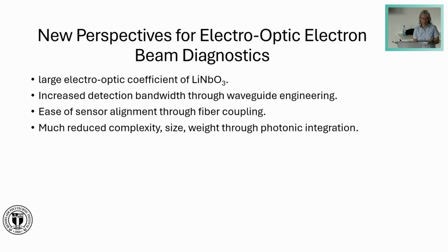If I come back to the new perspectives provided by thin film lithium niobate, it has a large electro-optical coefficient. It is about 10 times larger than zinc telluride and almost 30 times larger than gallium phosphide. So we can tremendously increase the bandwidth compared to bulk lithium niobate by using integrated optical waveguides, which allows us to minimize the mismatch in the propagation velocities. And since all the optical functionalities are integrated on a chip, there is much less complexity, much reduced size and weight. And since it is fiber coupled, it also eases alignment.